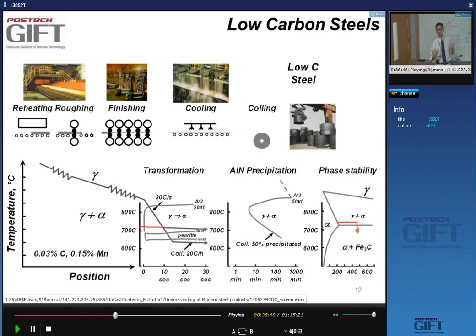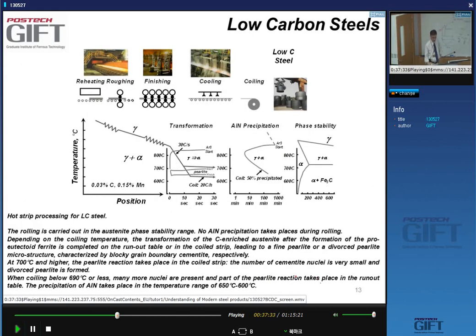You don't even get pearlite. However, if you go to lower temperatures and you go to the pearlite transformation on the runout table here, then you basically go right away through your A1 temperature and you make cementite, fine cementite actually. So the coiling temperature will not only have an impact on the aluminum nitride, whether or not it precipitates, but also the formation and the morphology of the cementite.